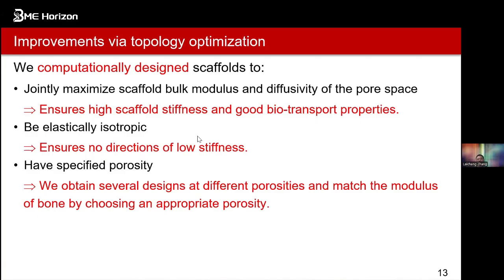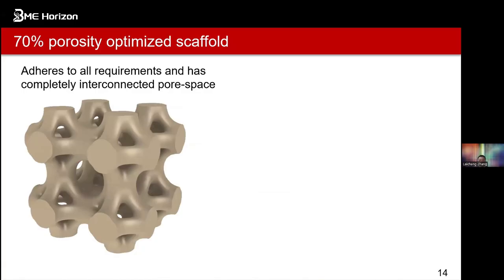Because if it is not homogeneous, that's why we try to ensure no direction of low stiffness. And also we have a specific porosity because for different structures, for example our bones in the head, face, and skull, and also our knees, shoulders, legs, and arms, of course the Young's modulus will be different. We will use one example to show later on. So of course, we try to obtain several designs with different porosities and match the modulus of a bone by choosing an appropriate porosity.